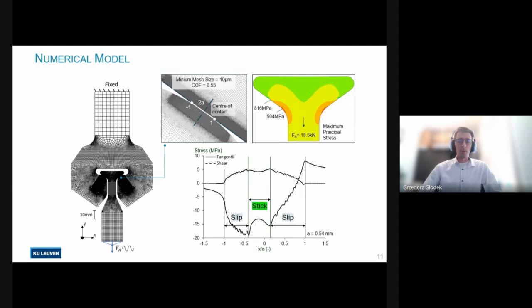Now, if we look at the stress distribution at contact, we can see that, again, the peak in the tangential stress is at the edge of contact, which likely drives the crack initiation there. And the tangential and shear stress distributions both reveal a stick-slip condition with stick in the middle and slip at the sides. So this is the most damaging condition, the most critical one to study.